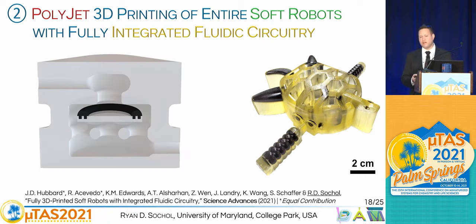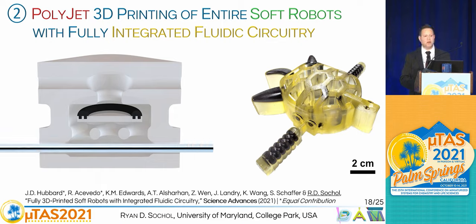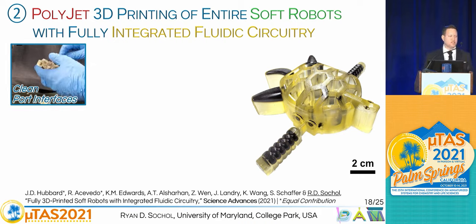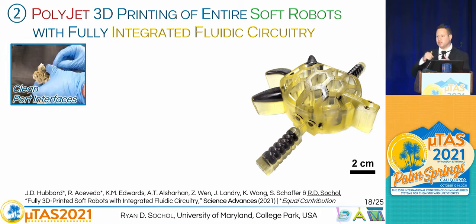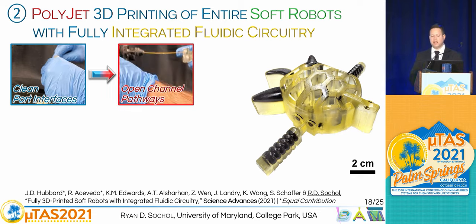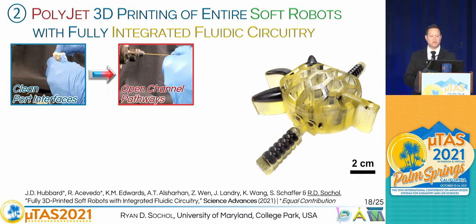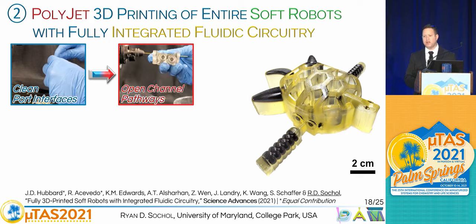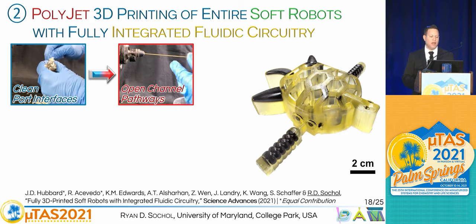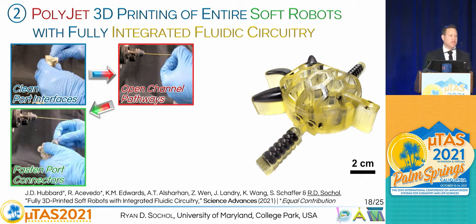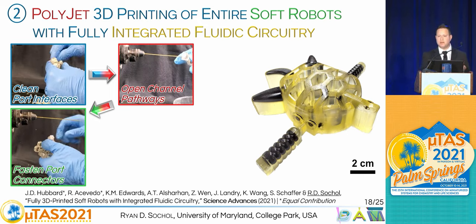The first is that we modify our component designs. Instead of something like this, we add some extra channels so that we're able to manually displace the support material out of our components. We do this through the entire system. There are four major steps. First, we manually clear out the ports that we've made. We have threaded ports for macro to micro connections, so you can do this by hand. Then we clear these particular pathways out by hand, like I just showed, and only a few of them need to be done depending on the design. Once that's done, you can take these external port connectors and fasten them into your system.